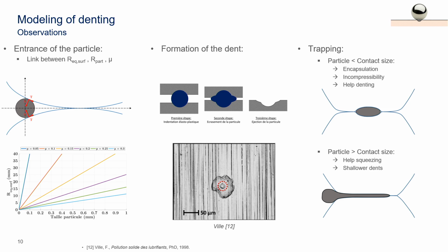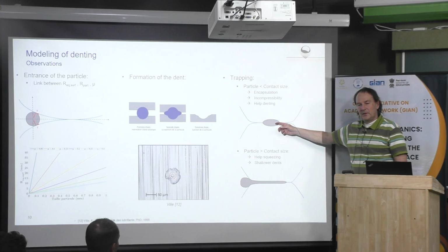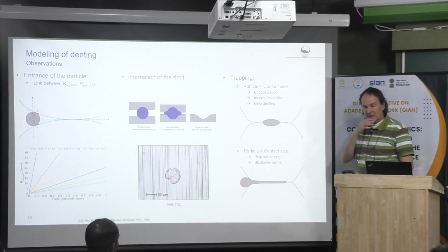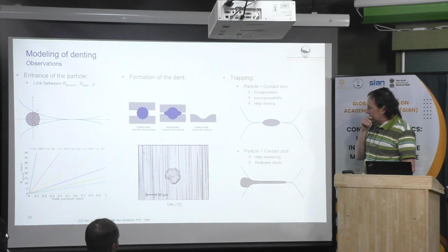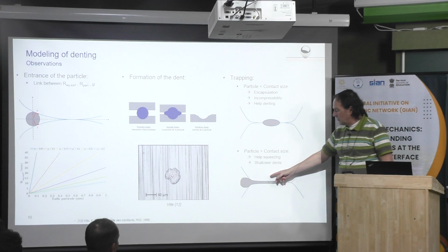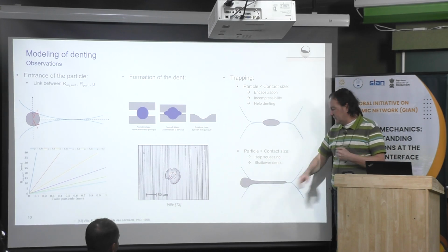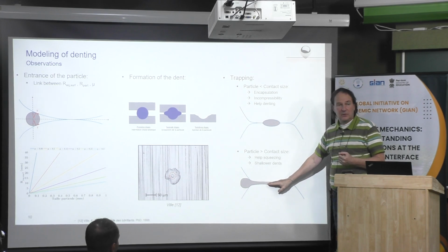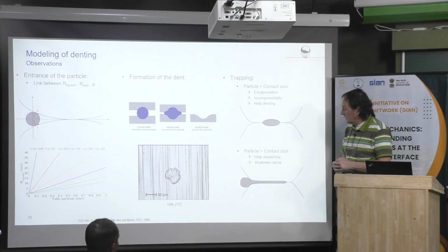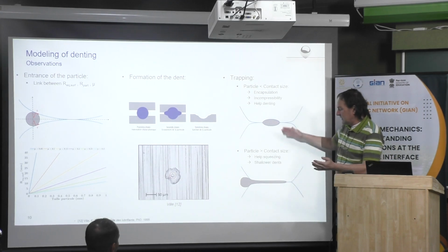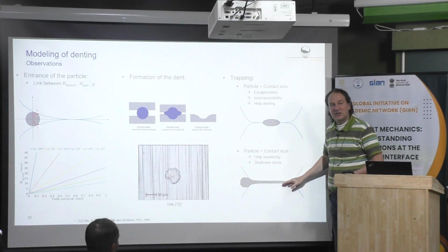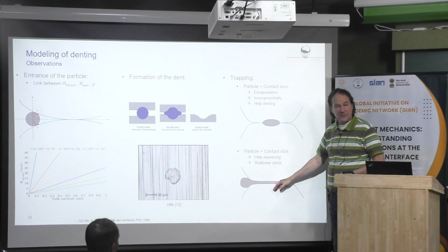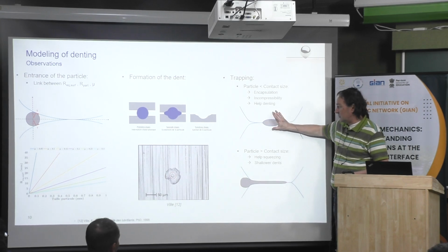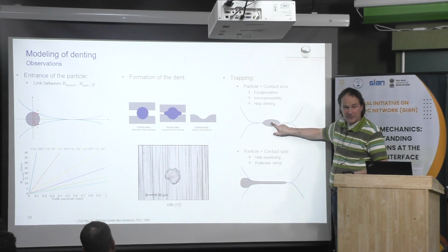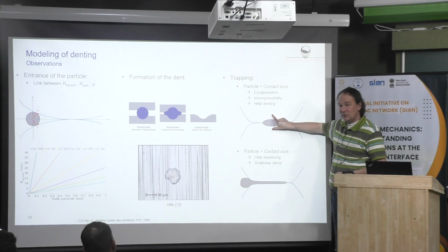Another interesting point is the effect of the size of the particle and the effect of the material. Okay. For example, imagine you have two steels in contact, and the particle is made of polymer. Then it's very soft. When you have a large particle, when you deform it, it will flow like that, and it will be ejected from the contact without marking the surface. Now, if you trap the particle within the two surfaces, even if it is a very soft one, because it is incompressible, this will mark the two surfaces.